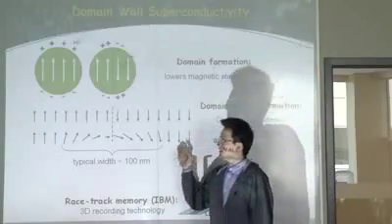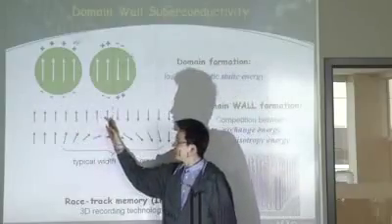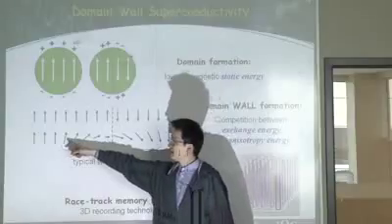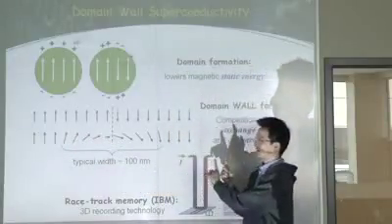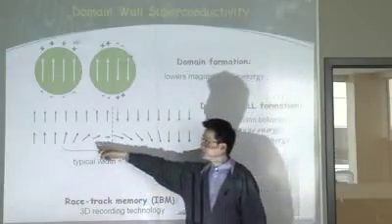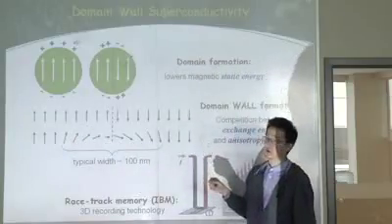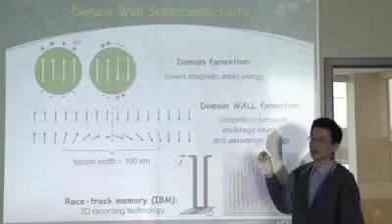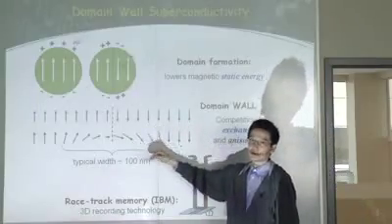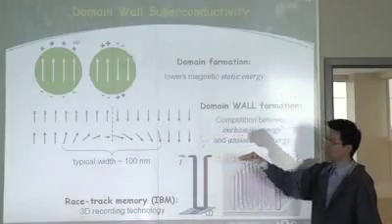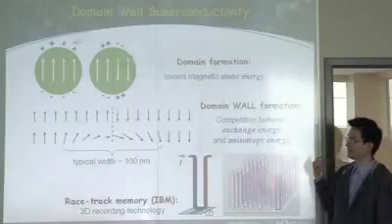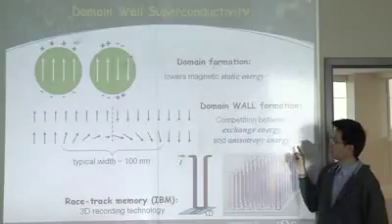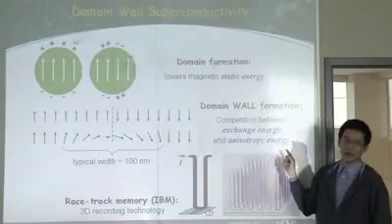So what the system does is it will try to spread the change over a very long distance. Now if you look at any two electrons neighboring each other, the change between them will be extremely small. So the magnetic exchange energy will be significantly reduced. But this process cannot continue indefinitely, because there is another energy scale that will come in. This is known as the magnetic anisotropy energy.